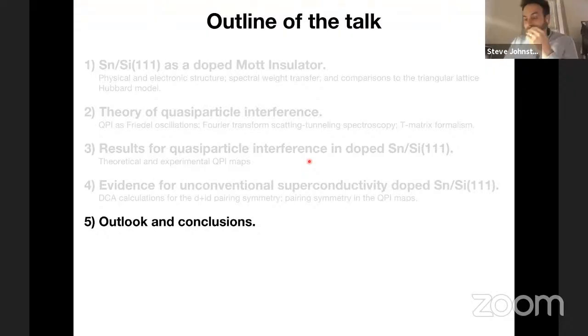Okay. So right now, Hanno's postdoc or former postdoc is doing some other measurements, specifically looking for edge states. In these chiral d+id superconductors, you expect to have an edge state. So right now we're hunting for that, and this is why we haven't published this QPI image yet. But we think we have the DCA results combined with these QPI images. I think that gives us pretty compelling evidence that it's really a d+id chiral superconductor.